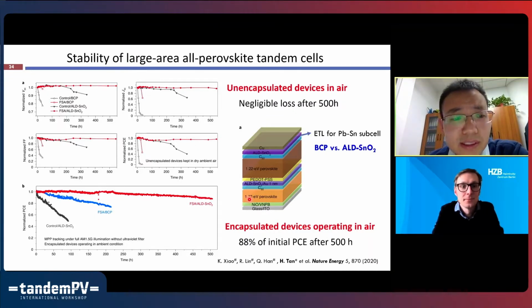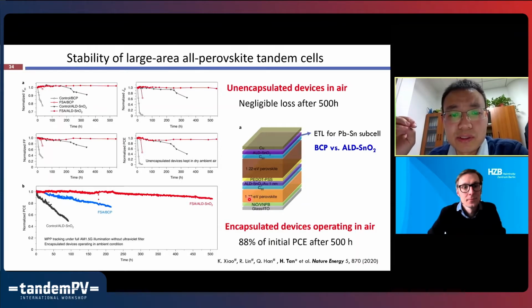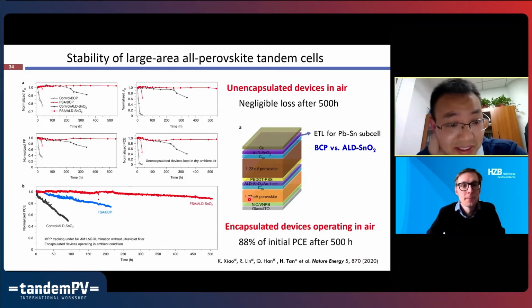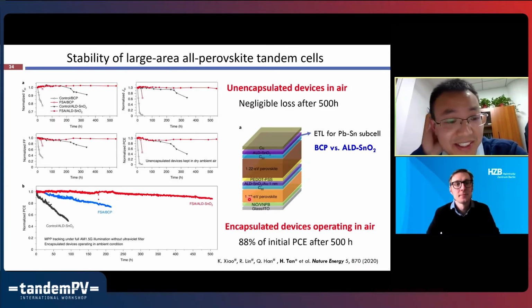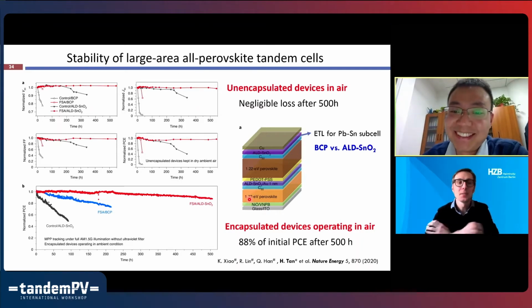Even in my lab, not everyone can make very good performing devices on top of the mixed lead-tin perovskite. So I think maybe the control of the water injection, and also the temperature, and also the purge time could be quite critical. But we haven't studied this in much detail. So. That sounds like an interesting topic.